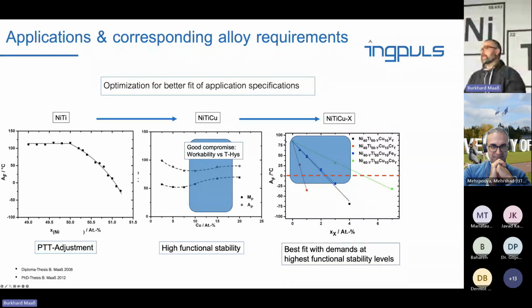You see that if we do this with NiTi copper, and we have done this for several copper contents on the B2 to B19 prime side, but also on the B2 to B19 side, what you see here are results of copper 10. The curves look more or less exactly the same for copper 5. Just the hysteresis is bigger. So we can play with the copper content for having a larger or a smaller hysteresis, and we can put in these elements for reducing or for fine-tuning the AF.